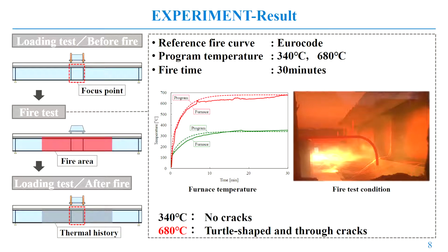Next slide shows the results of fire tests. This figure indicates the relationship between furnace temperature and time. After the fire test, we checked the bottom of slab, and there are no cracks at the program temperature 340 degrees Celsius. However, another program temperature 680 degrees Celsius occurred some cracks.